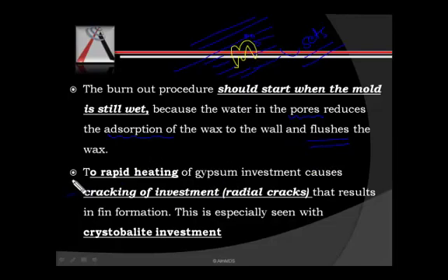Now, we do not advise too rapid heating of the gypsum investment, because as we know, gypsum cannot stand much heating, and if the gypsum is heated too rapidly, it results in cracking of the investment material. Later when the metal comes in, it will fill these cracks and result in the formation of fins on the surface of the casting. So the cracking of investment due to too rapid heating of the gypsum may result in fin formation, and this is more commonly seen with cristobalite investments. And this is a very common MCQ.